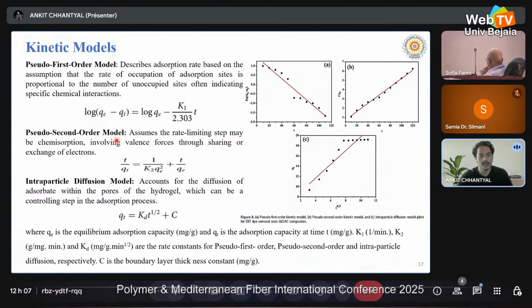And the second order model suggests whether our adsorption is chemical or not, involving valence forces through sharing or exchange of electrons. And this is the equation: t by Qt is equal to 1 upon K2 Qe square plus t by Qe, where K2 is the rate constant for the pseudo second order model. And the third one is the intraparticle diffusion model, which accounts for diffusion of adsorbate within the pores of the hydrogel, which can be the controlling step in the adsorption process. And this is the equation, and these are the graphs taken from the paper. The first one is for the pseudo first order model, the second one is second order, and the third one is the intraparticle diffusion model plot.